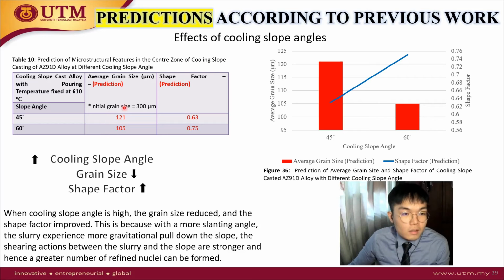And applying the similar percentage of reduction in grain size, we predicted these results and this graphical result. And with higher cooling slope angle, we obtain a smaller grain size and a higher shape factor. This is because with a more slanting angle, the slurry experiences more gravitational pull down the slope. The shearing actions between the slurry and the slope are stronger, and hence a greater number of refined nuclei can be formed.